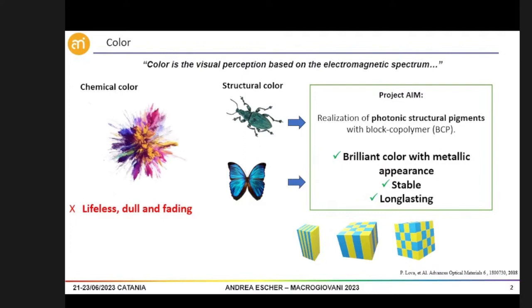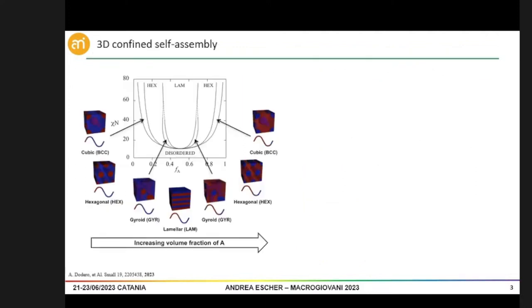So, I've just said that we are interested in the use of block copolymers, and in particular we want to use block copolymers because of their self-assembly properties. Using this phase diagram, we can predict the nanoscopic domain structure inside our pigments, and in our case, we are focused on the lamella structure, just by controlling the volume fraction of the block copolymer.